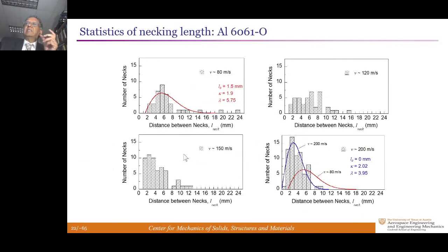You can also get the statistics of the distance between the necks, and just by collecting all of the 100 specimens and sorting out their distances between necks and collating them with the speed with which the ring expanded or the strain rate. So the ones corresponding to expansion of 80 meters per second and 200 meters per second are overlaid here, says that as the strain rate increases, there are more fragments, the distance between the necks decreases, and there are more necks in each one of the specimens. It seems this is driven purely by statistics.